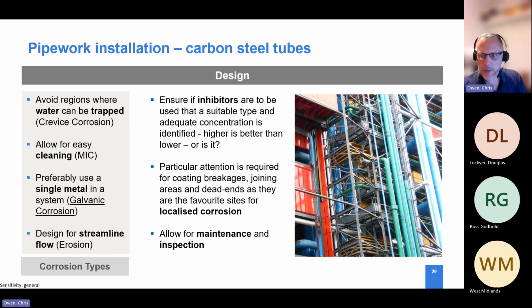And again, whilst inhibitors can be used as a means of mitigating the risk of corrosion, we'll touch on the fact that, certainly from some of the evidence we've seen, making sure the inhibitor is in the right quantity and circulated right through the system can be a bit of a challenge, which can give people a false sense of security. We've dosed the system, we've got an inhibitor in, so it must be okay. But if that inhibitor is the wrong inhibitor, the wrong strength, or not getting around the system, then you can have other issues which are going to cause corrosion.